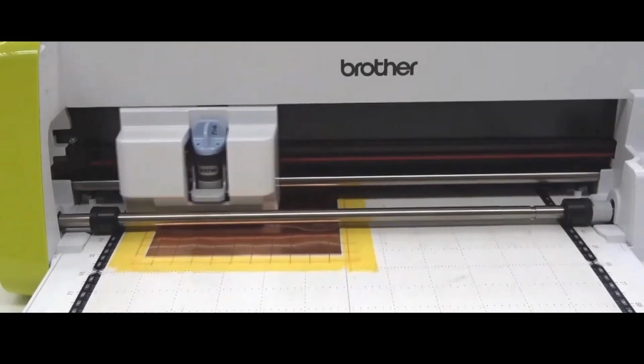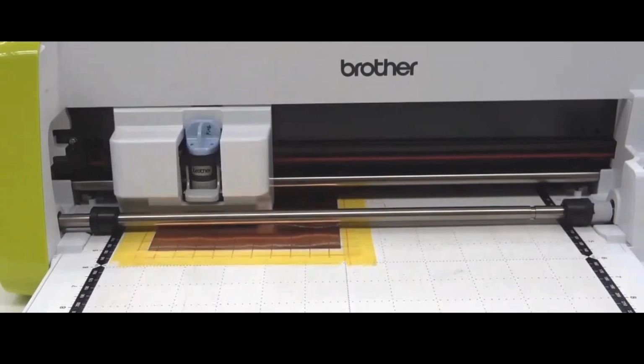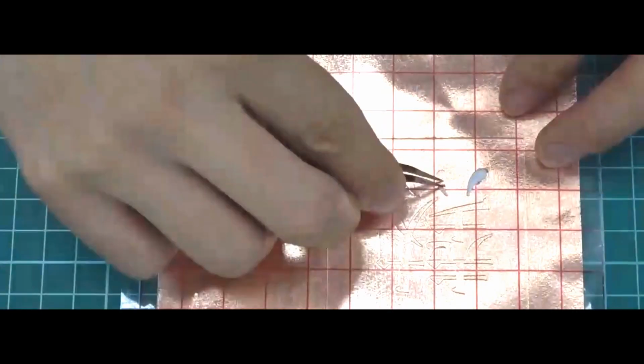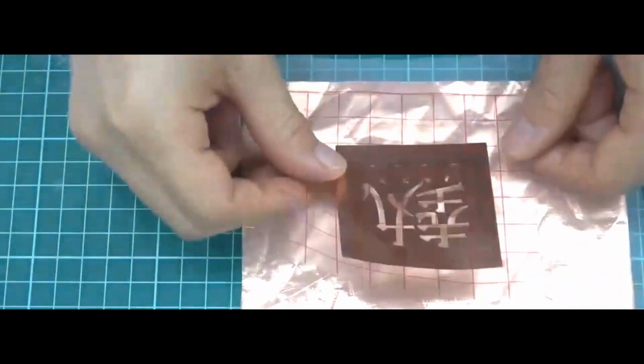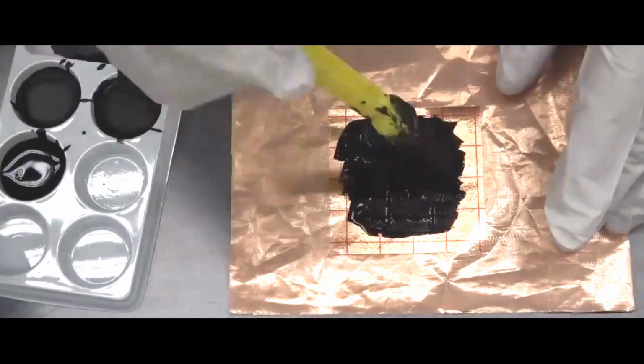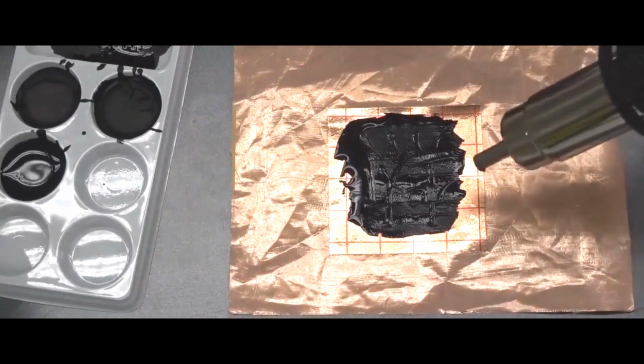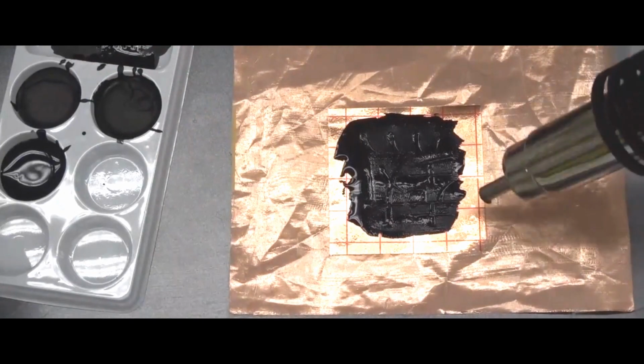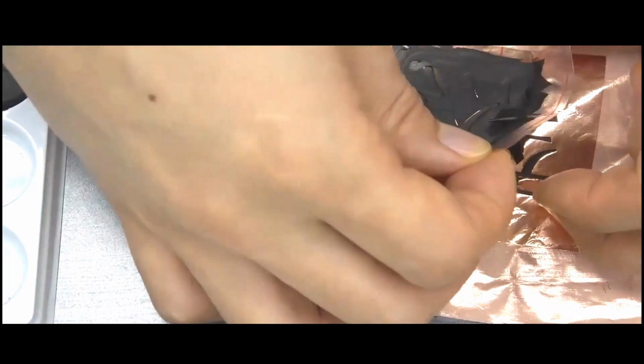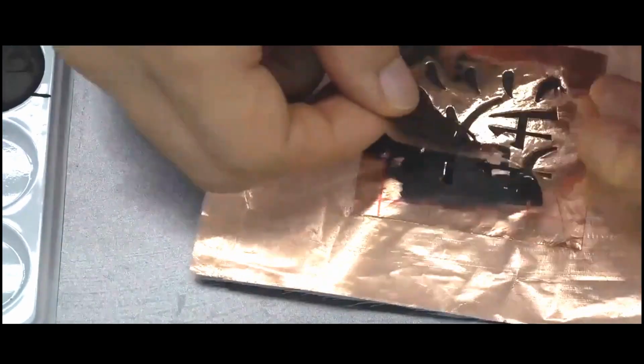We then use the cutting machine to make the stencil mask by cutting another copper sheet into the target shape. We manually clean the residue and use a transfer tape to attach the copper stencil mask as a positive electrode to the top of the screen mesh. We then evenly painted the screen mesh through the stencil mask with heating paint and dry it with a heat gun. We finally remove the painted stencil mask film from the copper electrode film.